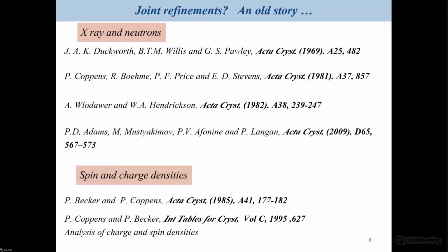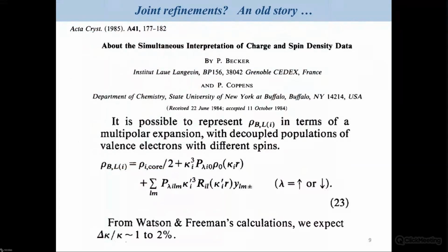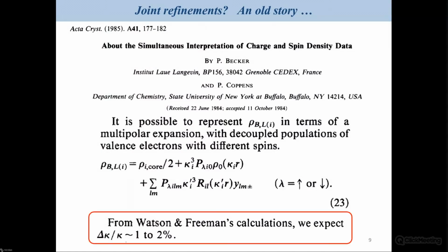I will particularly point out the work by Pierre Becker and Philippe Coppens, because in that work they claim that it's possible to represent the model by decoupling the populations of spin up and spin down. They also predict that this will induce a difference in expansion between the spin up and spin down distributions of 1 or 2%. This is something very interesting. I will come back to that point later.